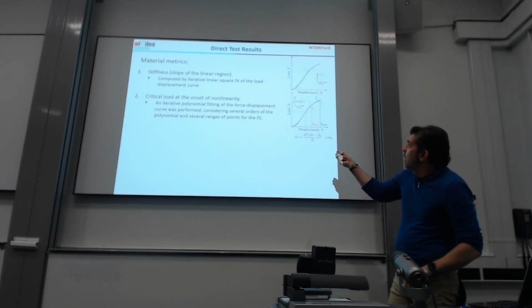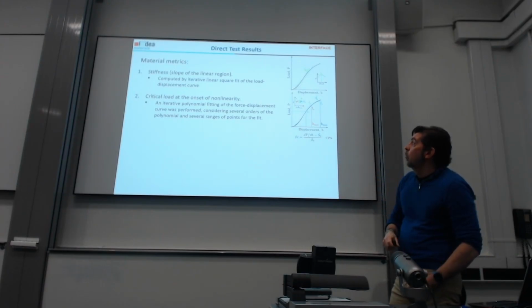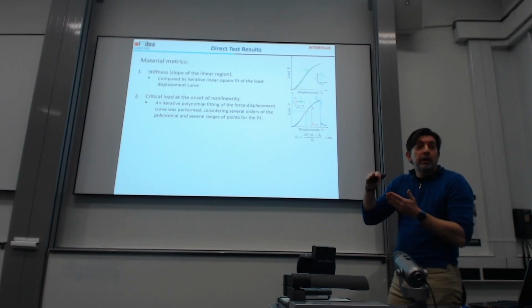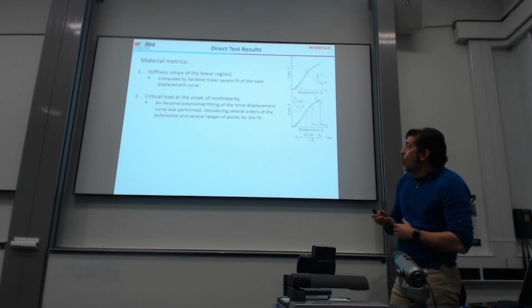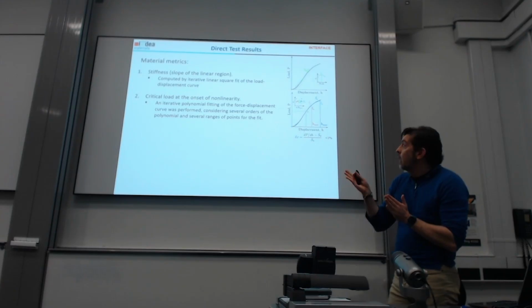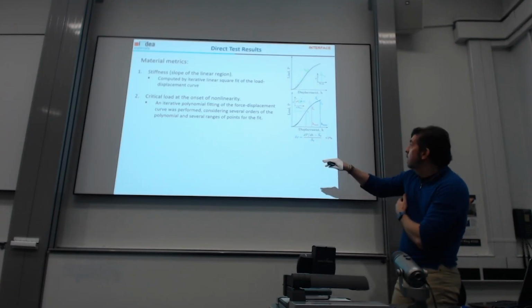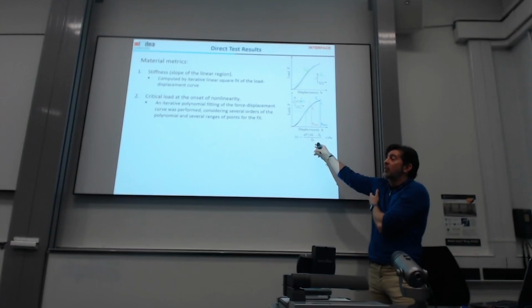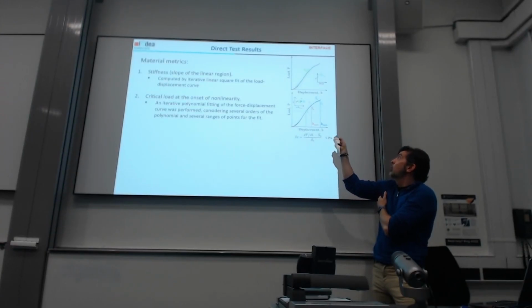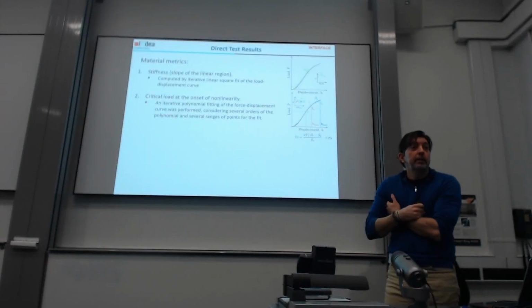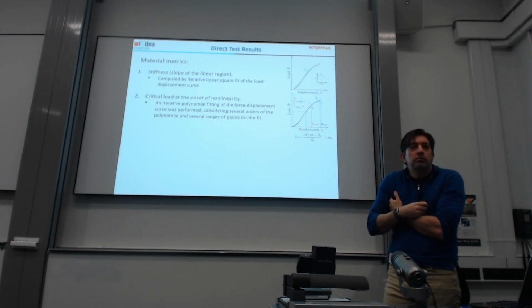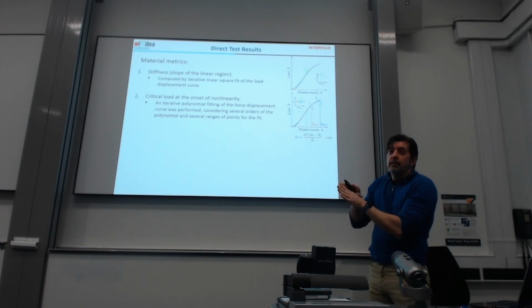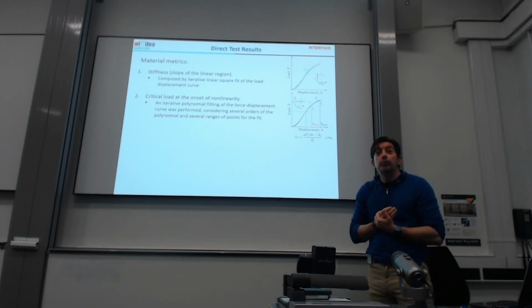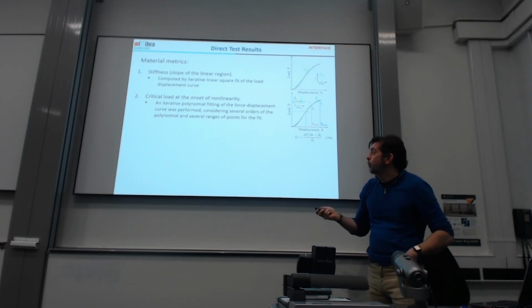We use an iterative linear least-squares fit of this linear part and then a distribution of the stiffness, and we get that. And for the critical load, we do a polynomial fitting with different orders for the polynomial and several ranges of displacement, and then we take the derivative, and when the deviation from the previously calculated stiffness is less than 1%, we take that as the critical load. But you can select what you want. You could just do 2% or whatever. It's up to you to get the critical load.